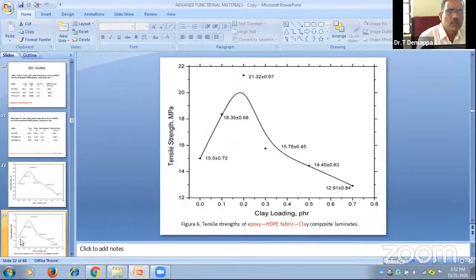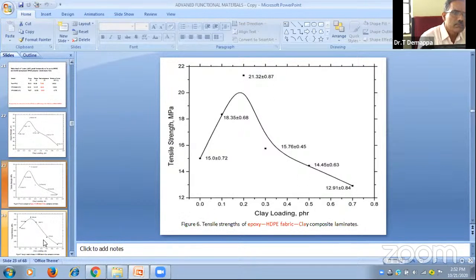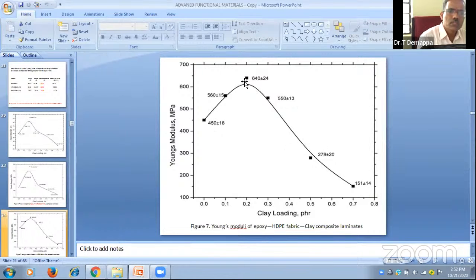Then come to the tensile strength. Tensile strength also shows the same behavior. Then Young's modulus also shows the same behavior. The maximum mechanical property or the maximum strength is found at 0.2 phr only. That is 640 megapascal. You see, without adding clay, it is 450 megapascal. You see the tremendous change that takes place. I think definitely clay will play a prominent role to enhance the mechanical properties, no doubt.